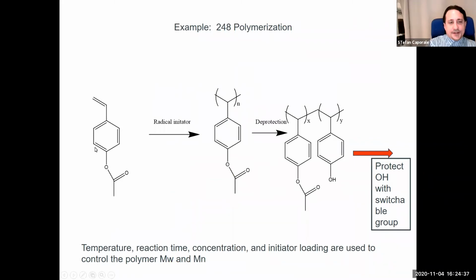So we have our vinyl material here. We use a free radical initiator so that we're able to polymerize it. You can't start directly from the phenol. That monomer reacts very, very quickly. I've blown the top off some test tubes in the lab, seeing how quick it goes. So it can be very explosive. So we actually start with the protected material, and then we go through a deprotection to remove some of this protected acetyl group and have the hydroxy, and then we protect that hydroxy further with the acid switchable group we want to use, depending on the type of resist for 248 that we're designing. Your temperature, reaction time, concentration, and the initiator loading are used to control the molecular weight of the polymer. That's your n repeat unit here, and that's just the size of your polymer.